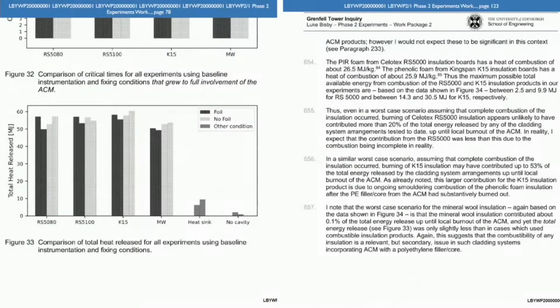I'd have to scroll up in the report to see, because we've made a number of comparisons. Some of those comparisons are based on the mass loss measured during the experiment. Some are based on the total mass measured at the end of the experiment. I think in this situation, we're talking about the total mass loss from the insulation products. So to back up a bit, before we ran the experiments, we measure the mass of the sheet of insulation that goes into the rig. So we weigh it. At the end of the experiment, we take that sheet of insulation off the rig, and we weigh it again. The difference is the mass loss.